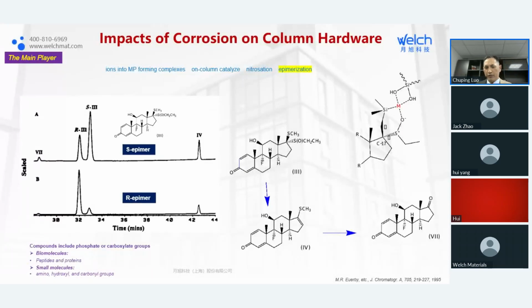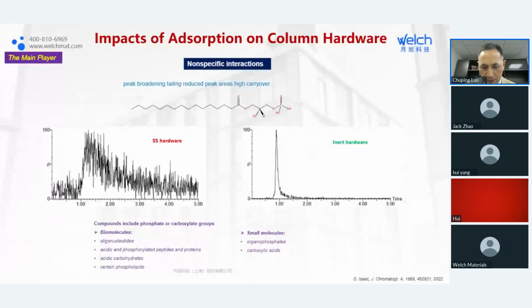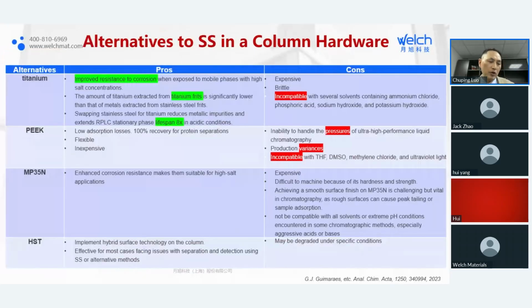So seeing hardware effects is very often; the signal is pretty weak. Like this compound, it has one phosphate group, and it's a pretty weak signal here. But if you use inert hardware, you see a pretty sharp peak. Then people say, oh, can we use a different material to replace stainless steel? Yes, you can. So the first example is titanium. By using titanium frit, you do see significantly lower metal extracted from the stainless steel from the system.